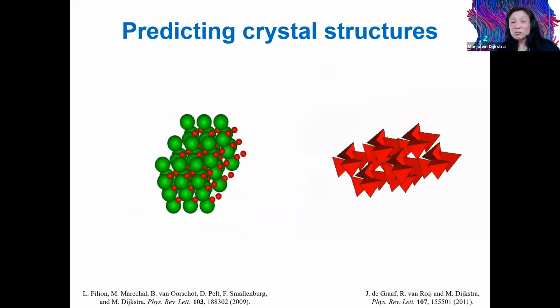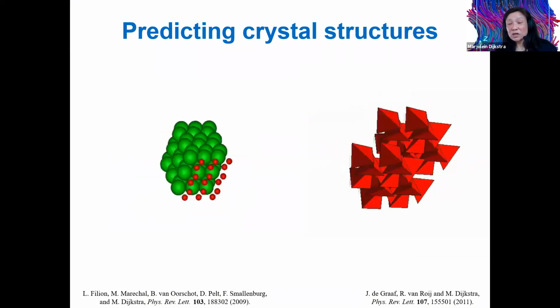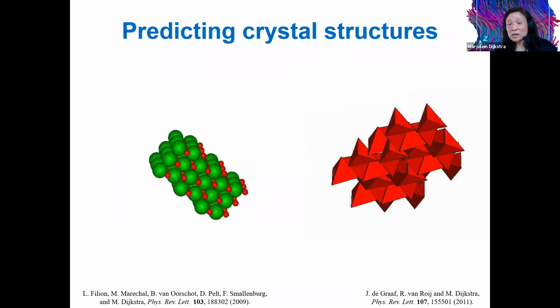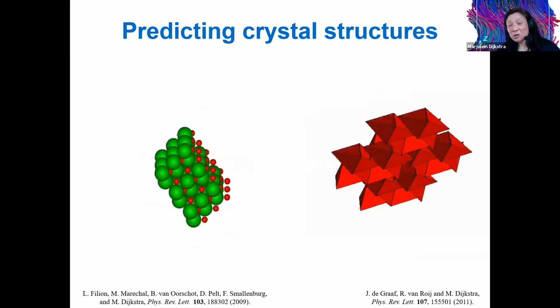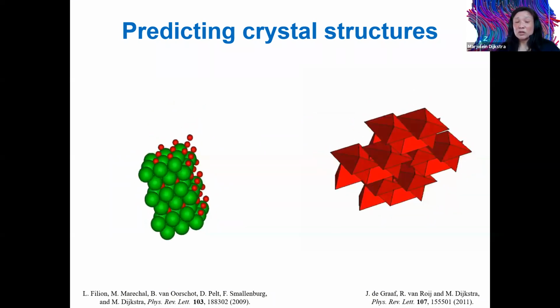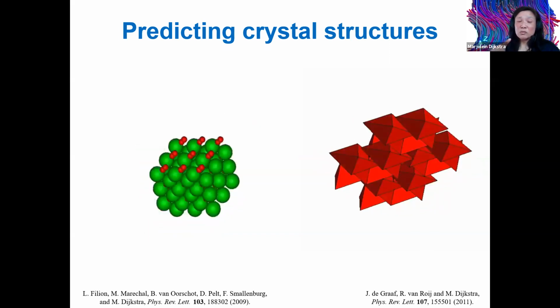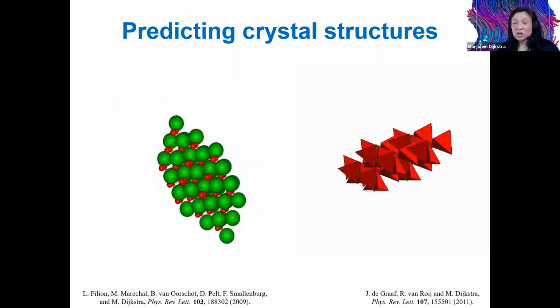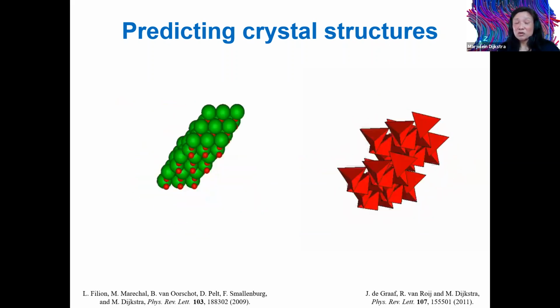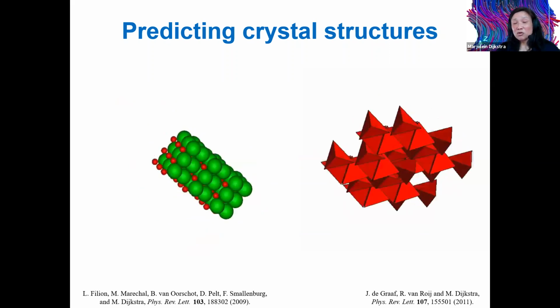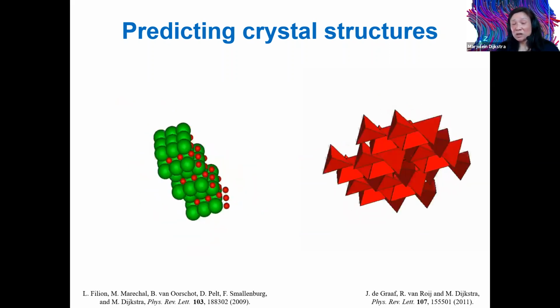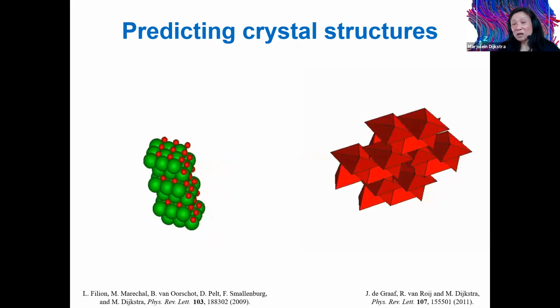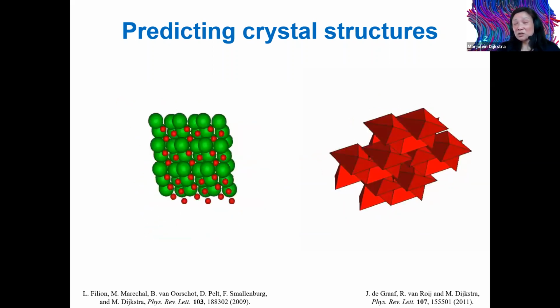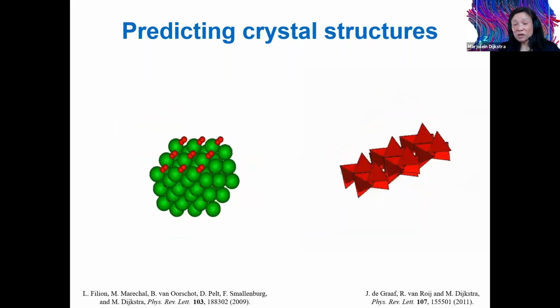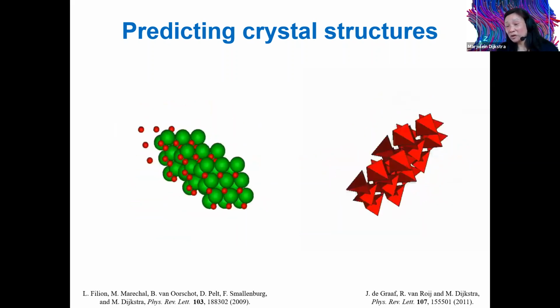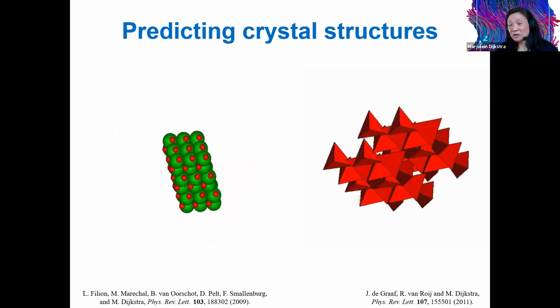And so here are two examples: a system of big spheres and small spheres, and also a system of hard tetrahedra. One can clearly see that the simulation box is floppy, it varies all the time. And this is very useful because you can scan over many different structures by just using this fluctuating simulation box. And by just using a simulated annealing technique where we increase the pressure in steps, we were able to find the densest packings. So this is, for instance, the densest packing of a binary hard sphere mixture, but also the densest packing of tetrahedra.